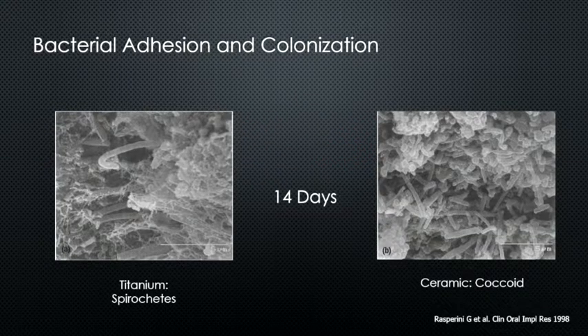They found that when you do some cultures after 14 days on titanium implants versus ceramic, you tend to have a more virulent species on the titanium. So no wonder you have more inflammation around metal parts and metal implants. And you have more cocci around ceramics.